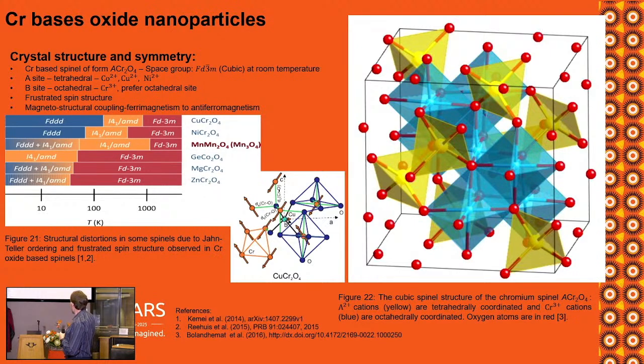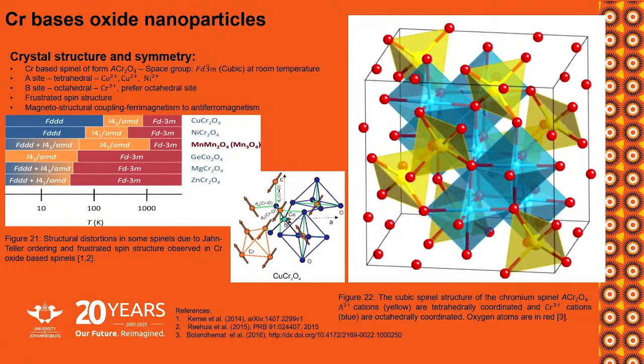If we start adding copper and nickel into the system, you can actually compress these. So those octahedrons, you can start compressing them. In some cases, you get the pull. You now change the distance between the atoms. What happens is the magnetism changes. And that's what this graph here in the figure actually shows you. You have structure change that happens, but these little edges for each metal actually show different transition temperatures. But also you've got different magnetism here.